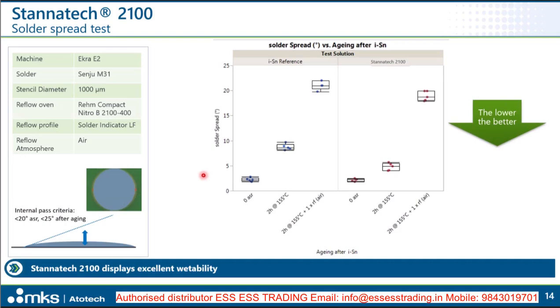The acceptance criteria for immersion tin layers are an angle below 20 degrees for as received conditions and below 25 degrees for aged conditions. What we can see in the graph is that we achieve the minimum requirements for all conditions, and that even the Stannatech 2100 shows slightly better results compared to the reference process. So we have slightly lower angles for sure. All of them passed.